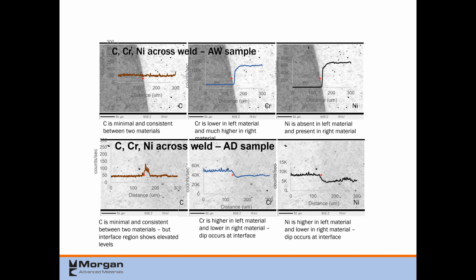theorized that the nickel and chromium content would be higher on one side and lower on the other. And sure enough, you can see a very sharp boundary there where the two drop off, and there's no change in the carbon content across the two materials. And at the bottom, they had a really hard time figuring out where the weld was. There's not much contrast there.